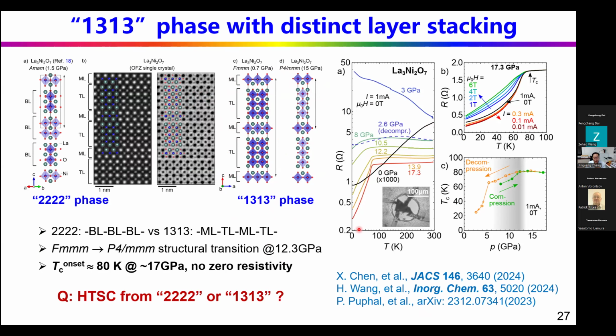So this raises a very serious question: whether the high Tc superconductivity comes from this bilayer phase or from this 1313 phase. In addition, the superconducting volume fraction is quite low. So that's why there's a lot of controversy, and a lot of debate about the nature of this superconductivity.